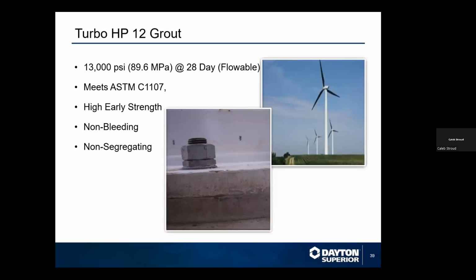Our Turbo HP12 grout is our heavy duty one. It's used a lot in the wind turbine industry. It can get up to 13,000 PSI at a flowable consistency at 28 days. And if it's in dry pack, it can even go higher, but more often than not, it's used in the flowable consistency. It still meets the 1107 specification, with high early strength, non-bleeding, non-segregating, just a great product overall.